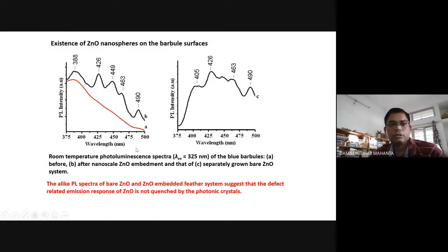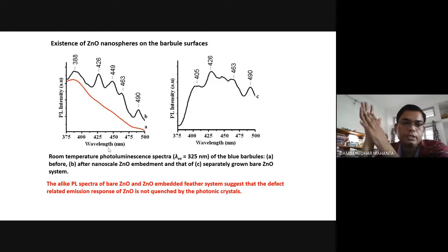Okay, so we have also taken photoluminescence spectra, because you know zinc oxide gives very good photoluminescence in the UV region, and it is very useful as far as lasing action is concerned and also upconversion. Now, zinc oxide possesses numerous defects like lattice vacancies, antisites, VO plus defects, doubly ionized vacancies, oxygen vacancies, then zinc sitting in oxygen position, oxygen sitting in zinc position, then you get multiple peaks. So it's a defective system actually, and this is simple zinc oxide.